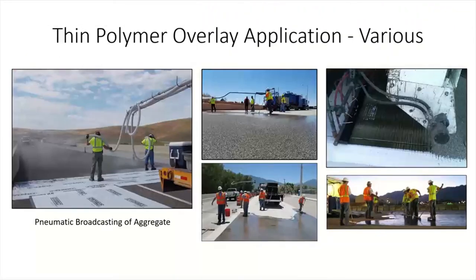Here's some other things that you can see. This photo on the left, they're not only using a pneumatic broadcasting system for the aggregate. What they did is they had a pump prior to where the aggregate was being broadcast, and they had a boom that went over the guys that were pumping and spreading the resin. So that accomplished one thing, that you didn't have to walk in the resin and you didn't have to drive on top of the aggregate.